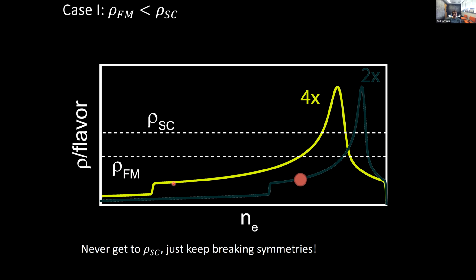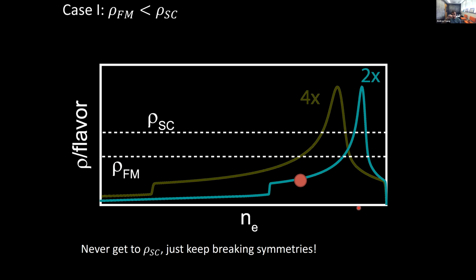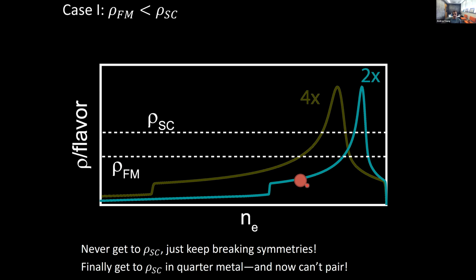So now we break the symmetry, we go to half the number of occupied flavors. The density of states goes down, and you never get to rho superconductivity, because every time you break a symmetry, your density of states goes down, and then you repeat this process. You continue up and down these curves until all symmetries are broken, and once all the symmetries are broken, you actually can't pair anymore because you don't have any degenerate electron states from which to make your condensate. Okay, so that's one situation, where rho ferromagnetism is lower than rho superconductivity.